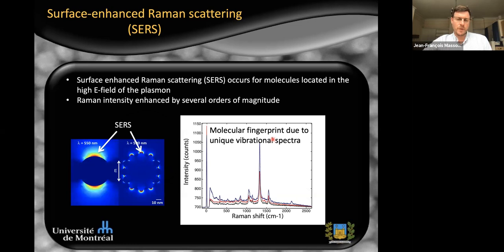One of the interesting aspects of that field oscillation is that it creates an antenna effect. In the case of spheres, you get a dipole when irradiated at the proper wavelength, creating a very high field in the proximity of the particles within the first couple of nanometers. If a molecule is bound in that enhanced field, it will experience a much higher Raman scattering cross-section, such that you can detect surface-enhanced Raman scattering (SERS) from even single molecules. The ability to detect single molecules is critical because you can identify which molecules bind to a particle by looking at the Raman fingerprint of the molecule, and each spectrum is unique for a single molecule.